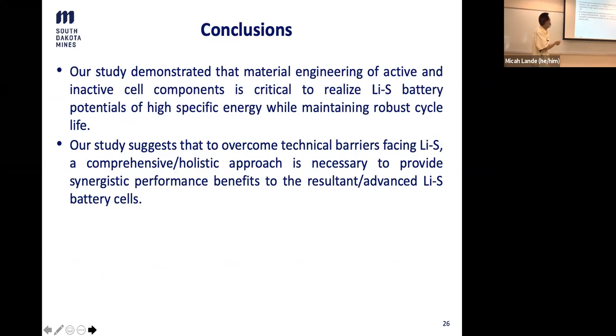We showed that our study demonstrated that the material engineering of the active and inactive material components is critical to realize sulfur battery's potential of high specific energy while retaining very long cycle life. Our study also suggests that to overcome this technical barrier for sulfur, we need a holistic approach that provides synergistic performance benefit to the resultant advanced lithium-sulfur battery cells. That's our conclusion from this study.